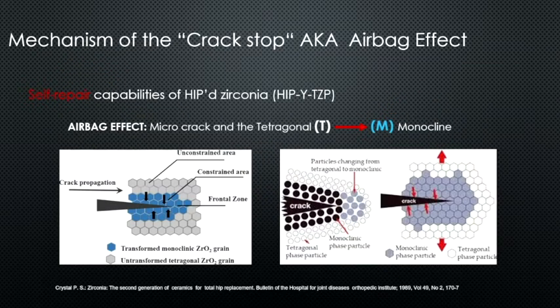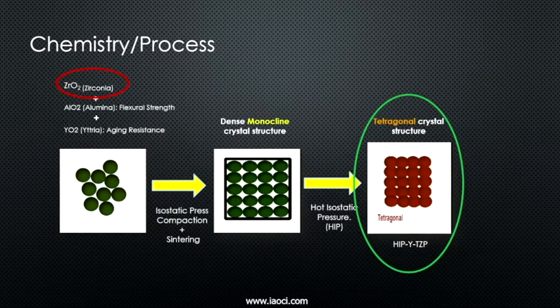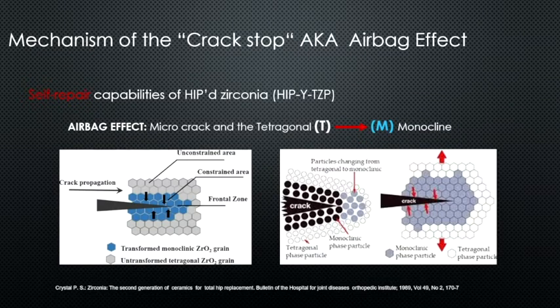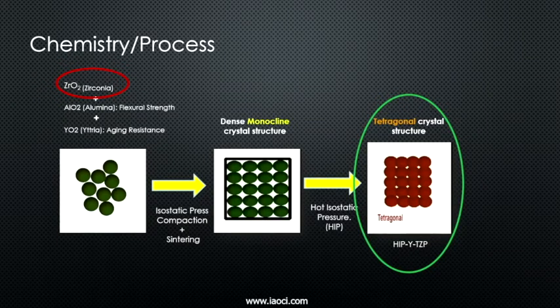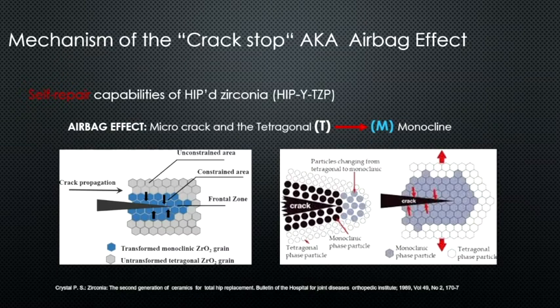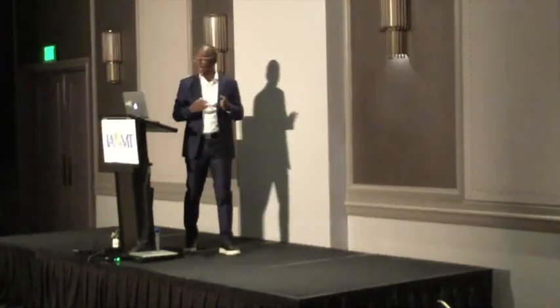Okay, so this is monoclinic, and this is tetragonal. If it's in the monoclinic stage and a crack comes in, because there are gaps, it tends to spread. But if it's in a tetragonal stage, if a crack comes in, the formerly squished parts here expand like a bag and stop the propagation of the crack. That's why they tend not to fracture, because they have what is called an airbag effect. So when a crack happens and opens a gap, it expands and stops the crack from propagating.